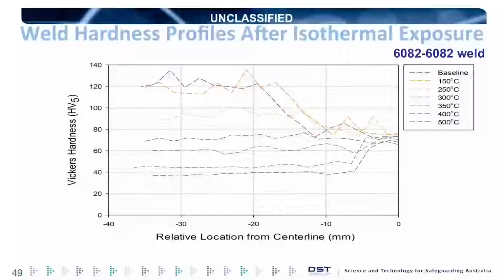This is just the welded sample for the 6082, I think. And again, the middle of the weld is here. The heat affected zone comes out here. You can see for the baseline, the hardness runs up here. And as we increase the temperature of the fire, the hardness drops quite a bit. But on this particular material, because of the alloying, as we continue to heat it, it actually recovers again as well. What happens if we have a fire of that magnitude on a ship?